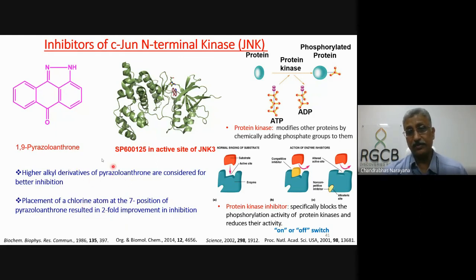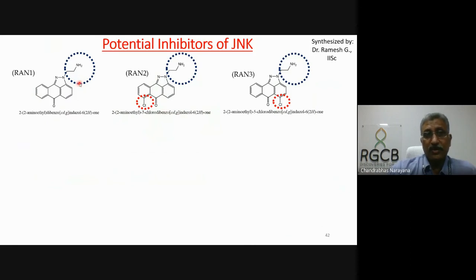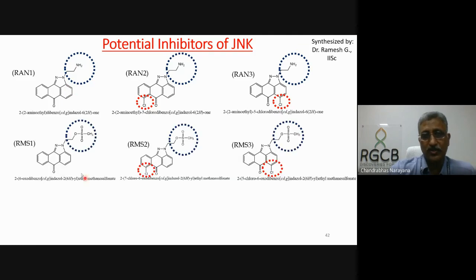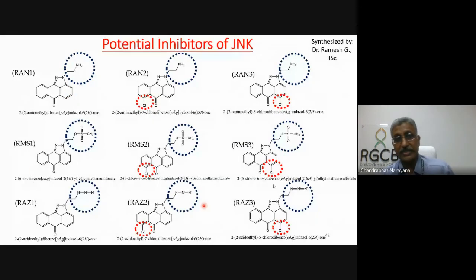He is an X-ray crystallographer, so he was interested in finding out how this particular molecule is binding to the system. So the kind of changes that were made is that we increased the hydrophilicity in this region by an alkyl chain plus NH2 and adding a chlorine, which is a hydrophobic group. So you change this and you make many new molecules, and you can see different types of molecules were created. So they were interested in knowing which of these can be quickly identified as a possible candidate for inhibitory enhancement. So that is what they were interested in.